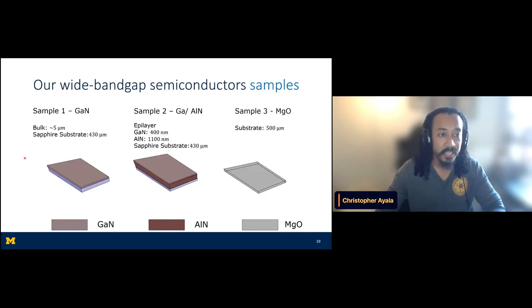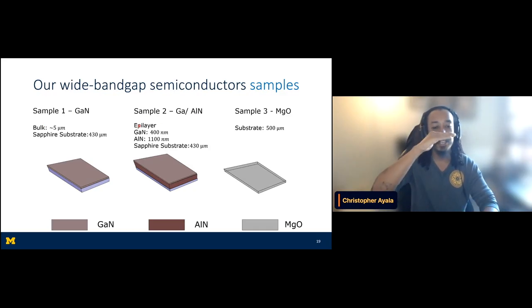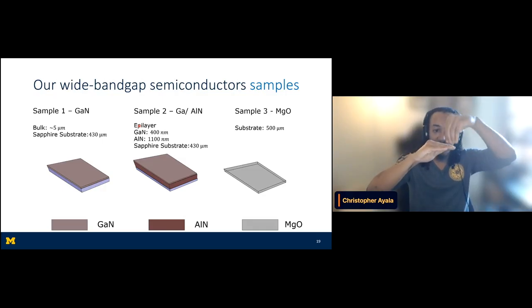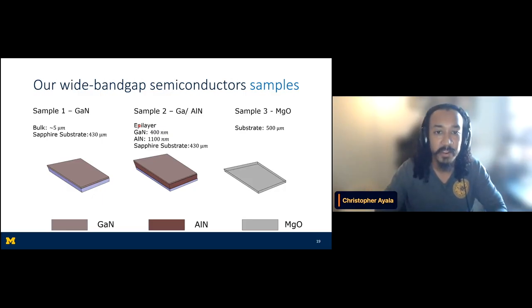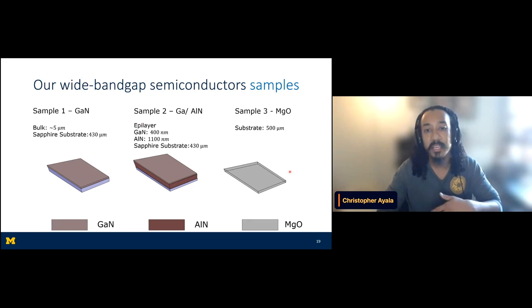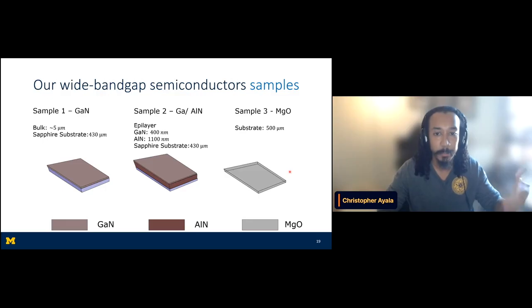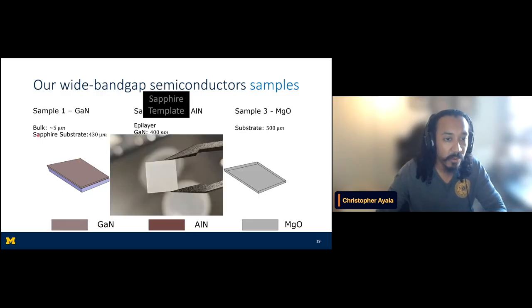The 3 samples that I am studying currently are gallium nitride in bulk form, gallium nitride in epi-layer form, which just means that you have one sample grown and then you're able to deposit the gallium nitride in a very fine layer and grow it in a way that minimizes defects. And the final sample is magnesium oxide, and we chose magnesium oxide as a control material that has been experimented heavily upon. As you may have noticed, both the gallium nitride samples are grown on what's called a sapphire substrate. So this is a real-life size to scale picture, and we study all of our harmonics in reflection geometry.